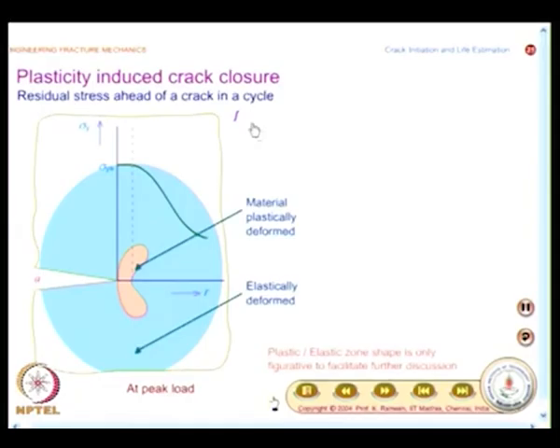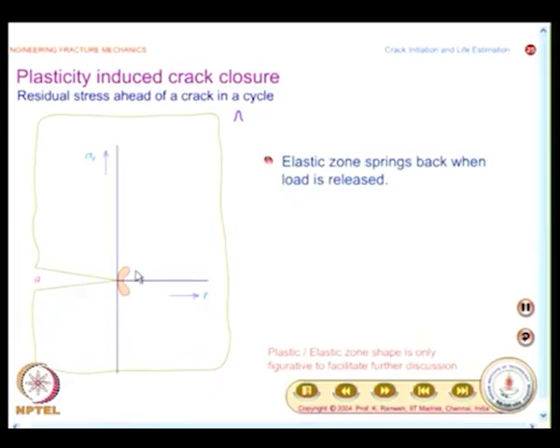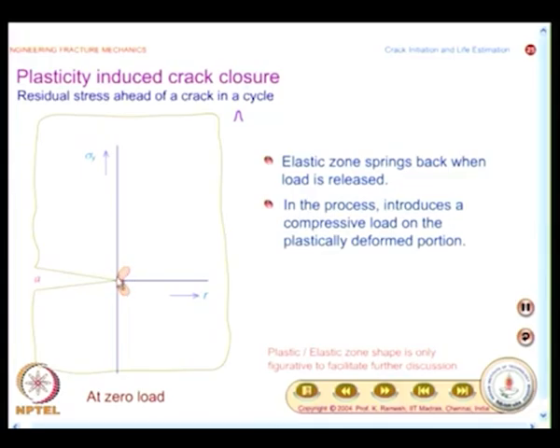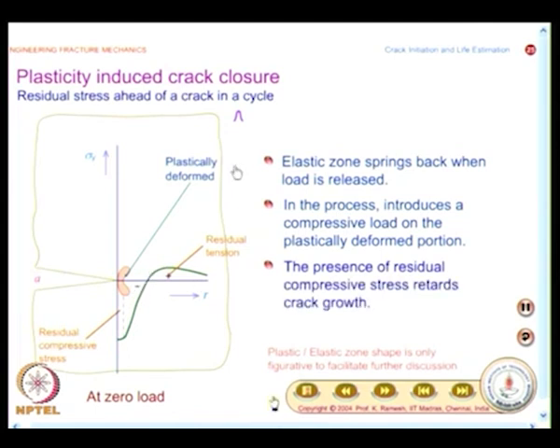Whatever has happened to the elastic region, it will spring back to its original position. If there is no plastic deformation at the crack tip, the spring back would be uniform all throughout, but because you have a plastically deformed zone near the crack tip, the elastic recovery will go and compress this zone. Let us see what happens pictorially. So, you will have a zone where this is still under plastic zone condition, much smaller in size, because of the elastic recovery of the neighborhood, and in essence you will have a residual stress formed at the end of one cycle. You know, this concept you will have to appreciate.